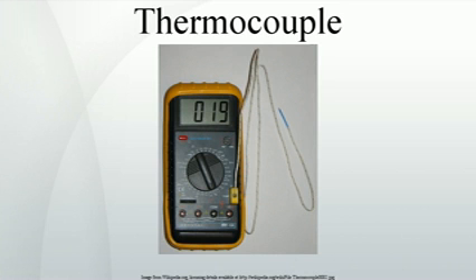Pure noble metal thermocouples, Au/Pt and Pt/Pd. Thermocouples made up of two different, high-purity noble metals can show high accuracy even when uncalibrated, as well as low levels of drift. Two combinations in use are gold-platinum and platinum-palladium. Their main limitations are the low melting points of the metals involved, 1064 °C for gold and 1555 °C for palladium. These thermocouples tend to be more accurate than Type S, and due to their economy and simplicity are even regarded as competitive alternatives to the platinum resistance thermometers that are normally used as standard thermometers.